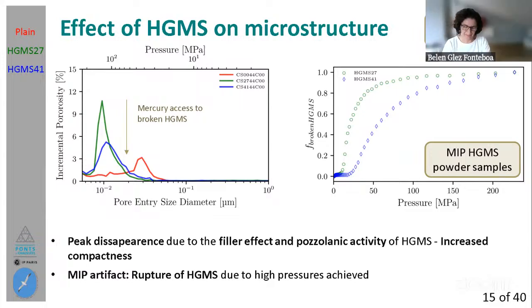Okay, perfect. My other question, I don't know if it has already been done, is about other possible tests like capillary absorption to confirm the interconnection of the pores, or even a permeability test for this kind of phase. I don't know why you have avoided this kind of test, or if it's a matter, I suppose, that when you start a research it is difficult to develop all kinds of tests. But these tests, in this case, to confirm the MIP results and the rupture of the hollow glass, I think would have been very suitable.